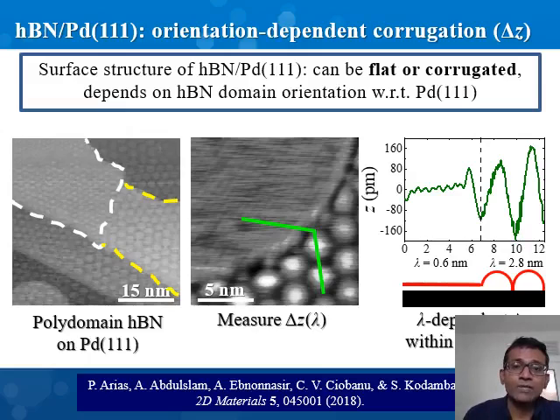And when we measure using scanning tunneling microscopy, the surface corrugation is found to vary with the moire pattern periodicity, which in turn varies with the relative orientation of the hexagonal boron nitride on the surface. It turns out that on palladium-111, hexagonal boron nitride can be weakly or strongly corrugated depending on the domain orientation, and even for the domains with almost the same orientation, depending on the extent of bonding.